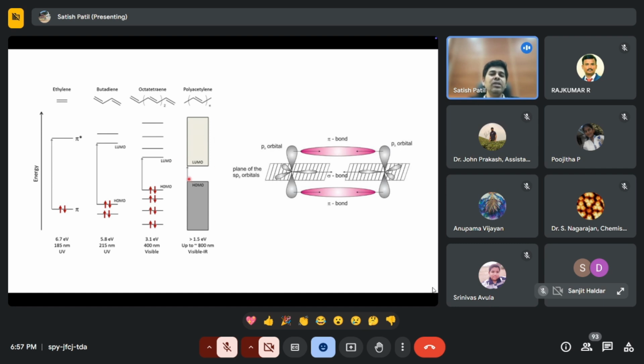You see that, as I mentioned, from ethylene to polyacetylene, this is the way the hybridization takes place in organic semiconductor. You see this, you have a pi bond. These are the PZ orbitals, they overlap. Then you have alternate single bond, double bond. You have a sigma bond, pi bond, a sigma bond, pi bond. Due to this, you have a pi bond cloud because of this PZ orbital overlap, and you get a sort of a transport through these kind of chains via these alternate single bonds and double bonds.